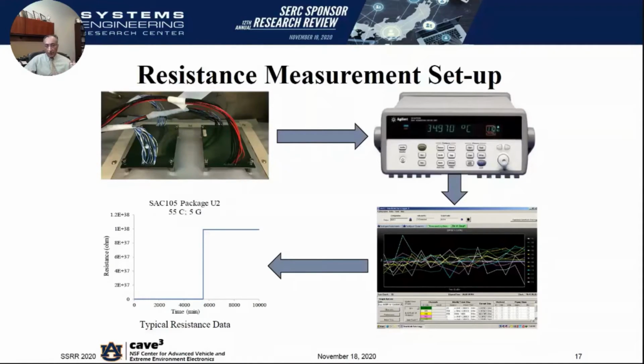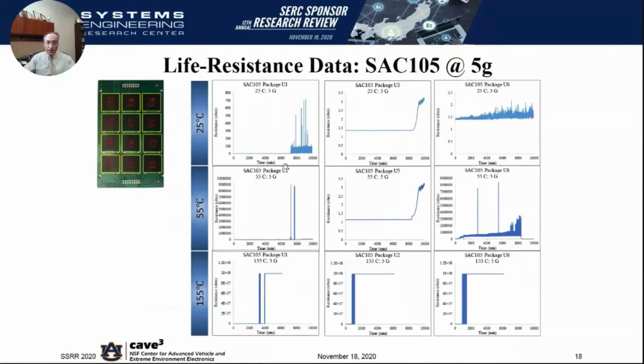So the board assemblies are daisy chain, as I mentioned. So these wires are the daisy chain assembly wires. And what we are doing is we are actually measuring the resistance in situ during the exposure to overlapping stresses of temperature and vibration, and logging the data using a data acquisition system. And then we log the time to failure as well. So here, I'll show you first data on SAC105. So this is at 5G.